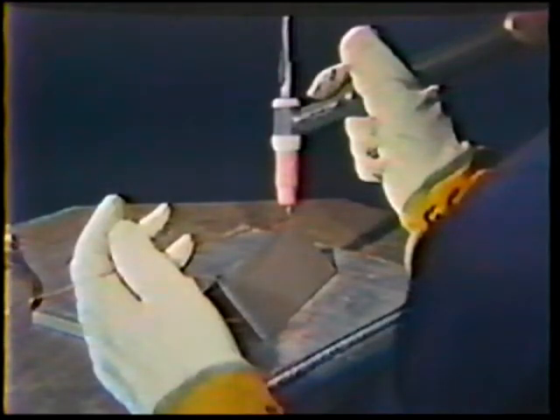The filler rod should be pointed at the leading edge of the puddle, directly over the weld axis, and then angled up about 20 degrees. As the torch moves evenly along the joint, the filler metal is added by moving the rod in and out of the leading edge of the puddle. Do not move the rod up and down. This can cause tungsten contamination and too much preheating of the filler metal.